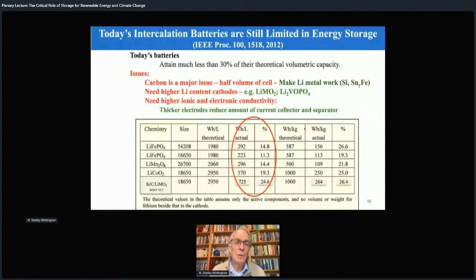So if we look at today's batteries, how do they stand? Can we improve them or not? And if you just look at the data I put inside that red oval, the percentage number there is the percentage of the theoretical energy density that we actually get in real cells. And you can see it's a tiny fraction, 11% to 25%. On a volumetric basis, it's about 25% on the gravimetric. So it's still a huge opportunity to increase that energy density. And we believe we should be able to at least double that.